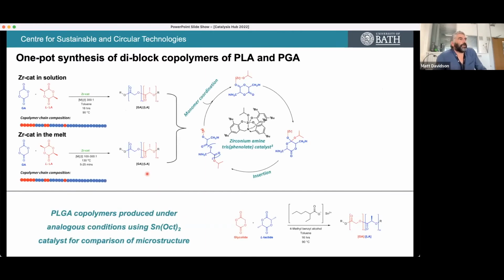So I'm just going to tell you a little bit about what we started doing here, or what Neve started doing a couple of years ago. We can do a one-pot reaction using our zirconium alkoxide catalyst that I introduced earlier. We can take the two monomers and make a copolymer out of it. We can do that in solution and in the melt. The mechanism for the polymerization is exactly as I've described. It's a coordination insertion mechanism, and that will give us some type of copolymer, anything from a perfect diblock to a completely random distribution of the two monomers used.